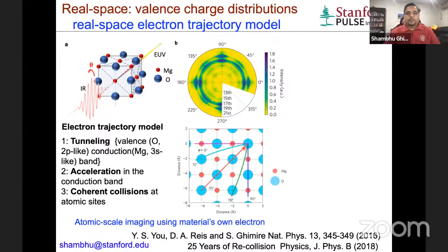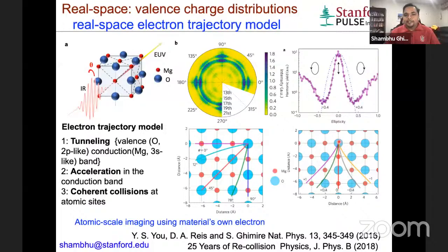This looks pretty lousy, but when you change the polarization, then it could be very interesting, as you can see here. This is when you change the ellipticity in the laser field from linear, this is the trajectory for linear, and this is for elliptical. And when you are circular, this trajectory is bent, right? And this is the measured harmonic spectrum as a function of laser intensity. And you can see the intensity changes dramatically. It is the highest at the linear polarization, and when you are elliptical, it goes down.